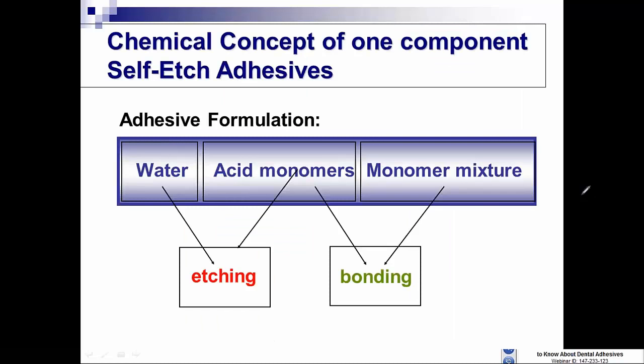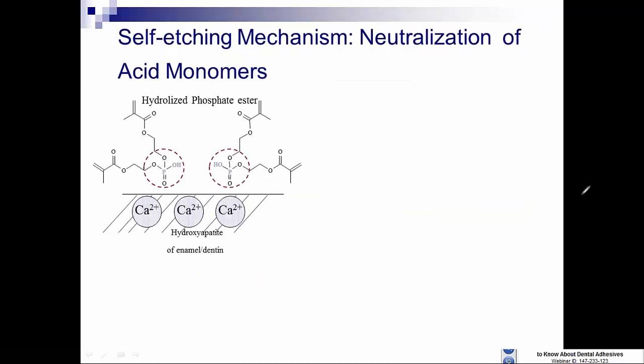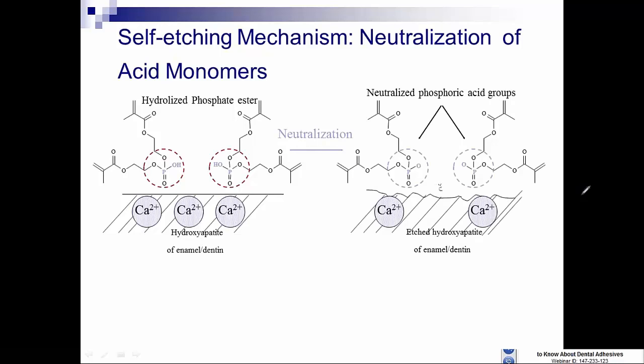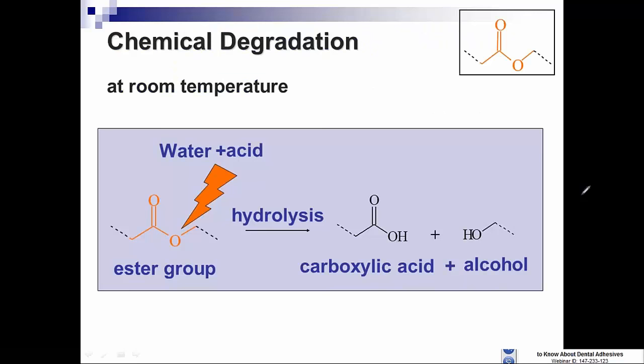Now these are not simple products. The one bottle systems are very complicated mixtures of water and acidic monomer with causes of demineralization, and then these acidic monomers with other resin materials to actually do the penetration and bonding. These acidic monomers not only demineralize, but also are neutralized by mineral apatite coming out and covalently bond to the mineral apatite or residual calcium in the tooth.